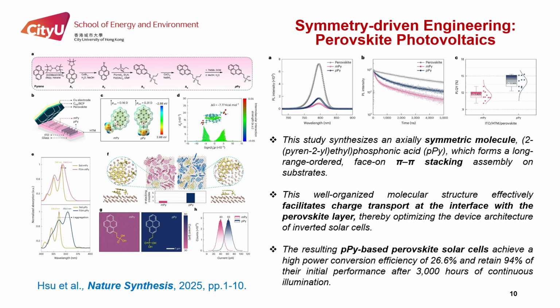The resulting PPY-based solar cells achieve a record-breaking power conversion efficiency of 26.6% and demonstrate exceptional stability, retaining 94% of their performance over 3,000 hours of use.